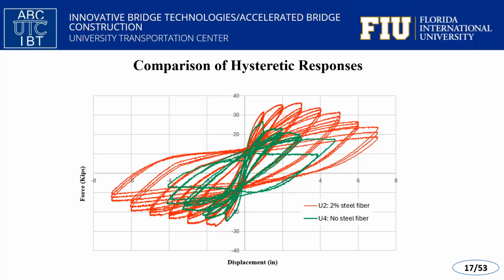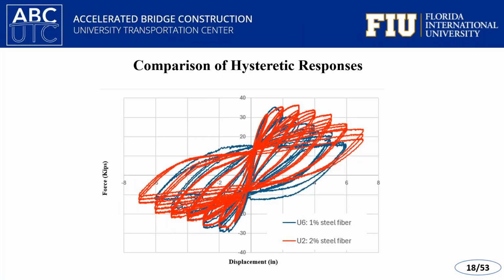A specimen with 2% steel fiber exhibits stable hysteretic loops. The steel fiber contributed significantly to crack control, delaying stiffness degradation and enhancing load carrying capacity. A specimen without steel fiber showed poor energy dissipation capacity and rapid stiffness degradation. The absence of steel fiber results in brittle behavior with significant strength degradation. This figure shows the hysteretic response of UHPC column with 1 and 2% steel fiber content. The 1% fiber specimen still shows improved performance compared to the fiberless UHPC column.